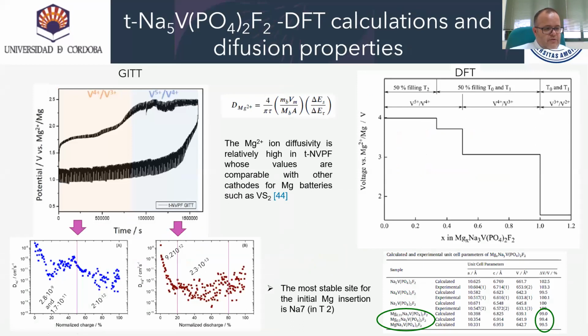Galvanostatic intermittent titration technique is applied to record one cycle at a quasi-equilibrium state. The calculation of diffusion coefficient could be expressed using this equation. The apparent diffusion coefficient during charge, which is sodium ion extraction in the magnesium cell, adopts a value around 3 times 10 to minus 9 to 2 times 10 to minus 11 square centimeter per second, which is the oxidation vanadium 3 to vanadium 4. And around 2.2 times 10 to minus 12 square centimeter per second after the oxidation up to vanadium 5.